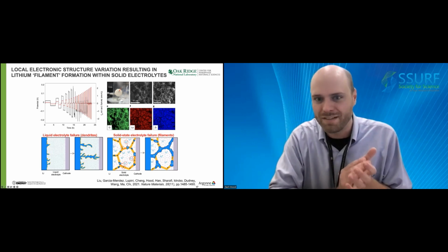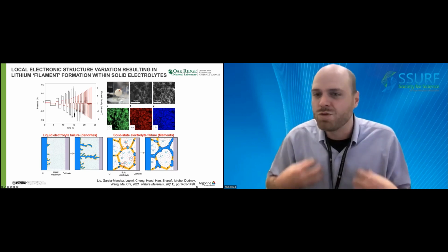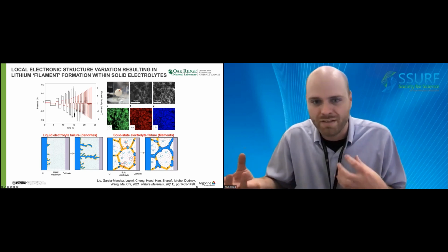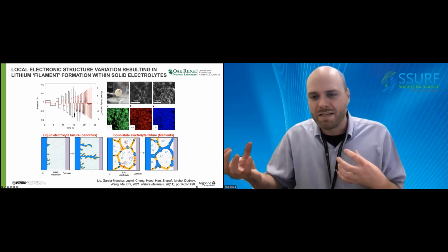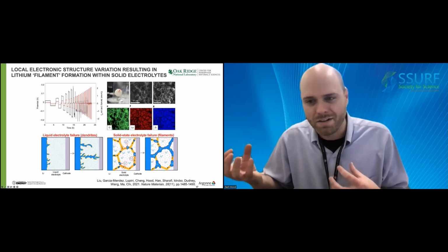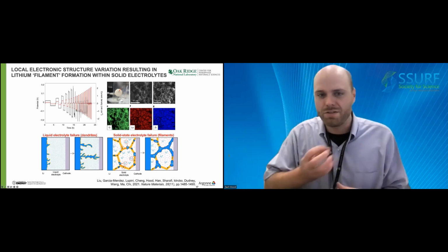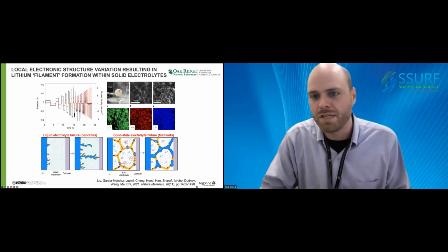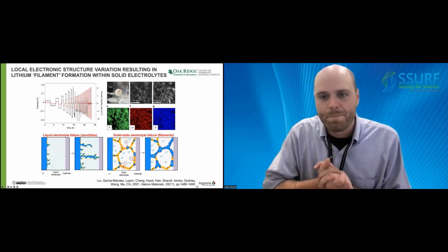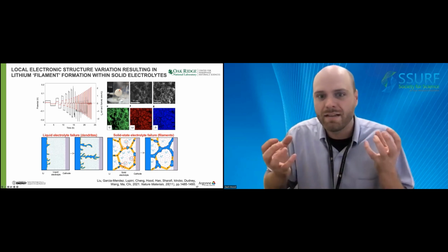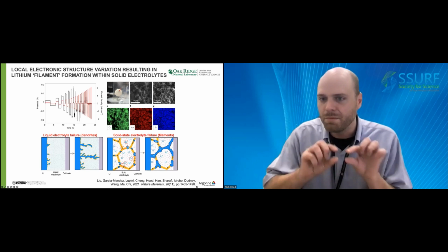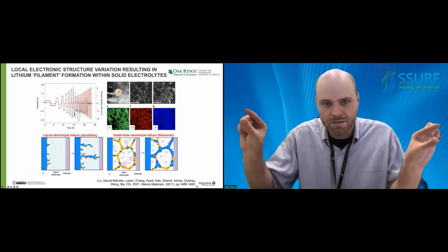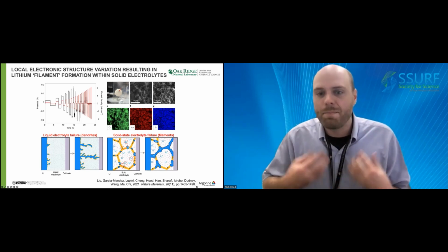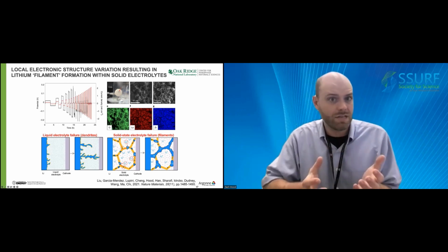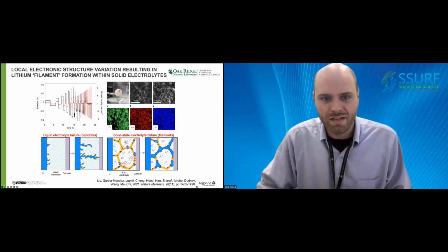future solid-state electrolytes. They highlight the importance of tuning not only the grain boundary chemistry and the electronic structure for these next generation ion conductors, but also the interface between the lithium metal anodes and these solid-state electrolytes. If a lithium conducting and electron insulating phase can be interposed between lithium metal anodes and the solid-state electrolyte, it may positively impact the current density that one could achieve in a full lithium metal battery.